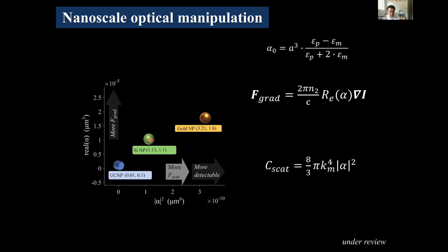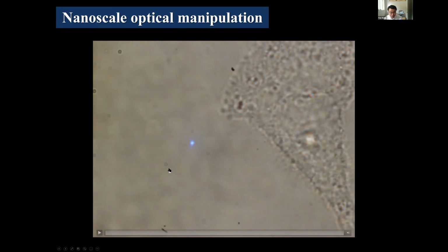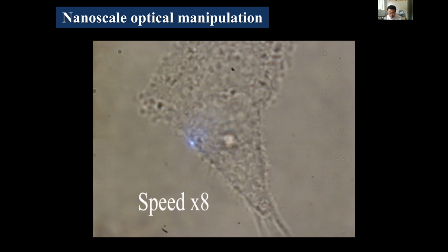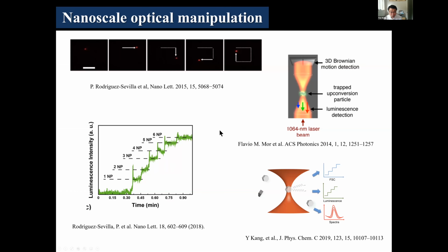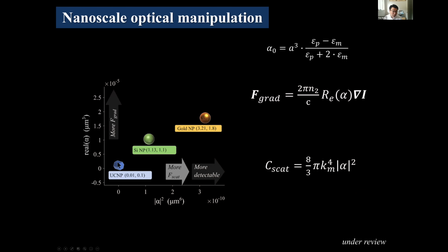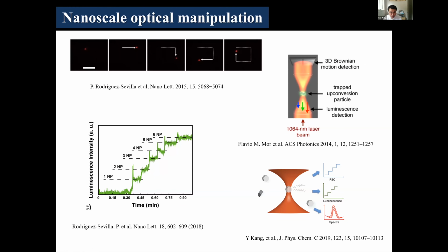Another candidate is the semiconductor nanoparticle, but the trapping force is also limited. For upconversion nanoparticles, the refractive index is really low, so the trapping force should be really small. But we've seen that even a single one of these nanoparticles is really easy to trap and squeeze into a cell, and not only our group, lots of other groups are doing similar things. Also, because this particle has temperature-sensitive emission, you can use it for temperature sensing. So this is amazing. But the question is, if you look at the previous image, the refractive index is really low, so why are we seeing this strong effect? People still don't know.